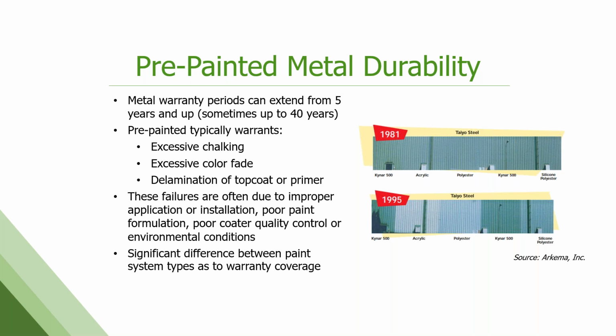This example we have here has been around out in the industry a long time. This is a building in Japan that was built as an experiment in this blue color out of several different types of paint. You can see there's SMPs, there's the Kynar, there's polyester, and an acrylic, which we didn't talk about today. Acrylics were used much more frequently 20, 30 years ago than they are now. And then just over 15 years or so, you can see how significantly different the color fade has been between these systems. And like we talked about, you can see that the Kynar 500 really hasn't changed at all, while the SMP and the polyester have changed quite dramatically.